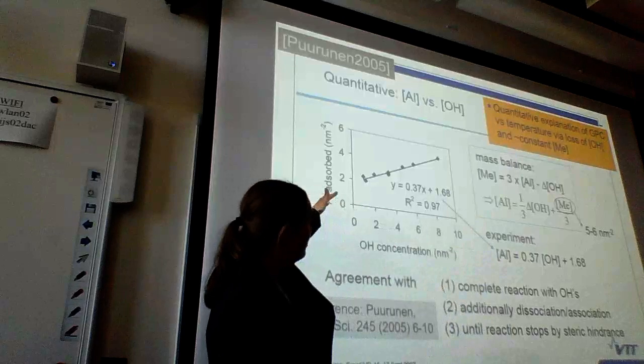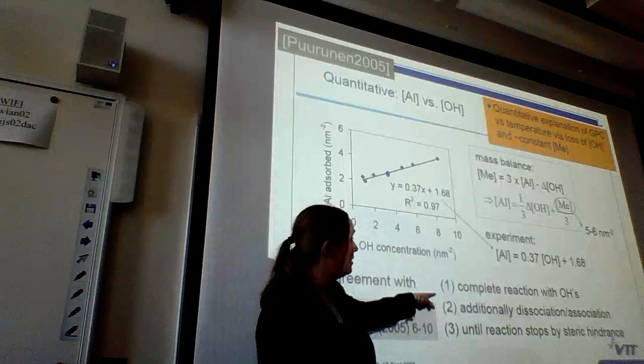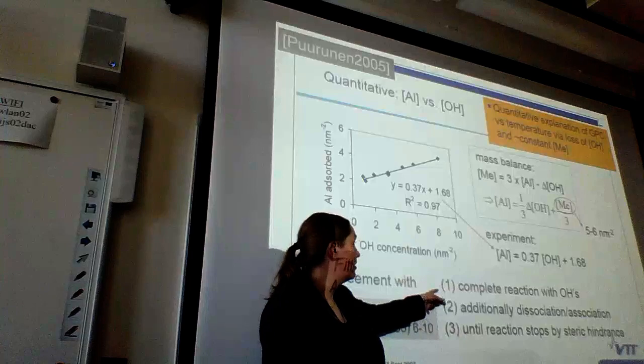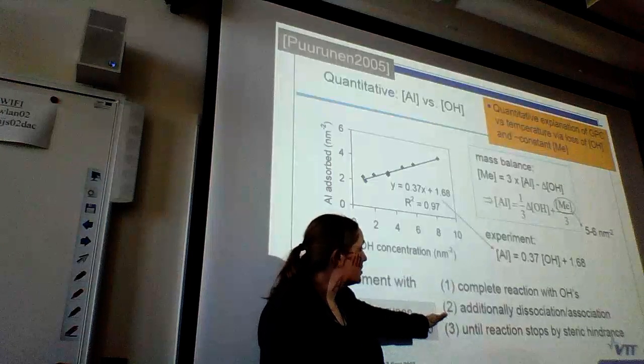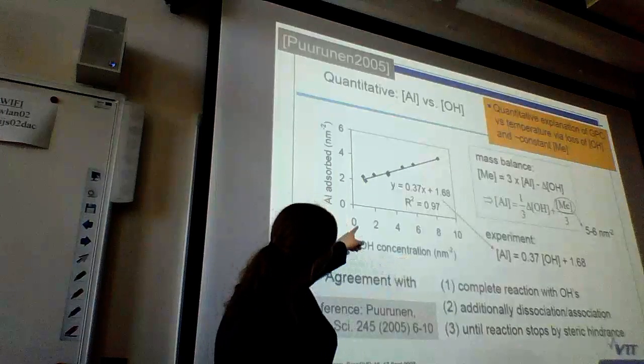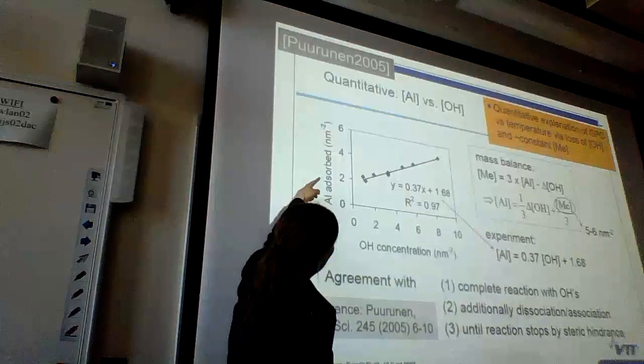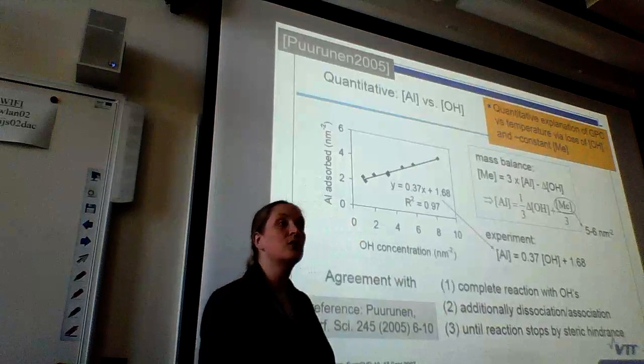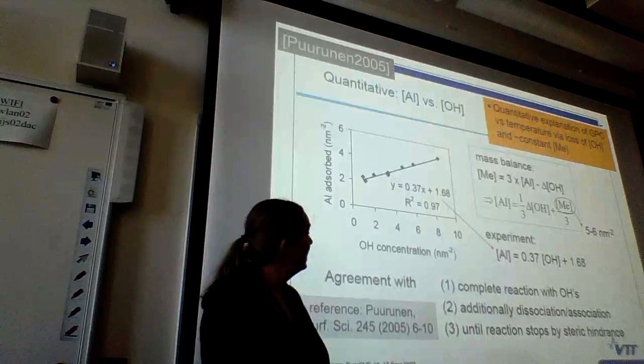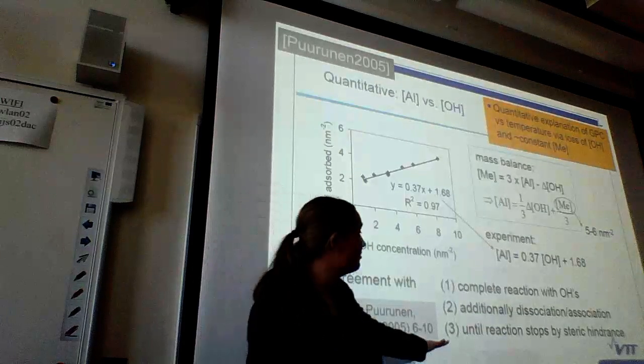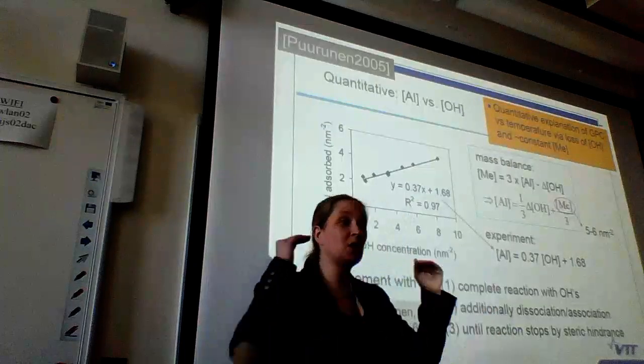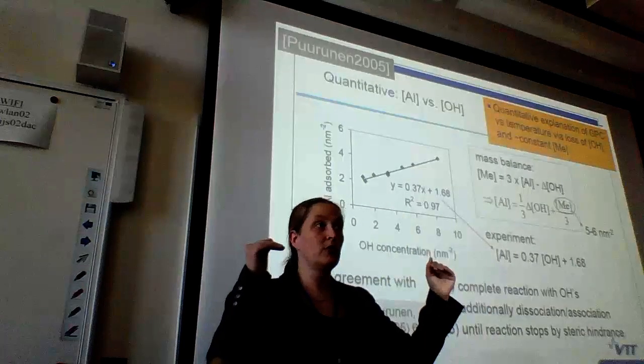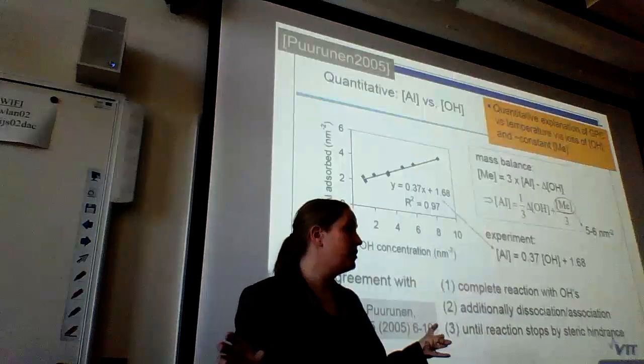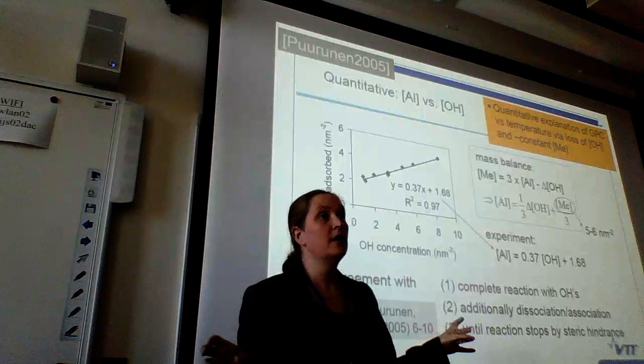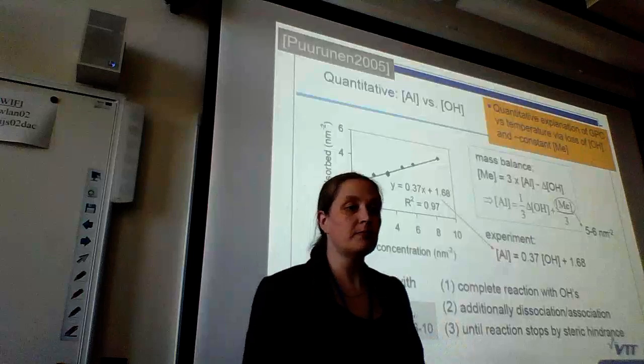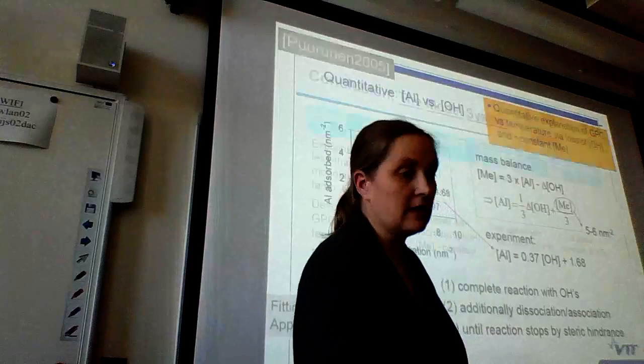So this experimental result is in line with complete reaction with OH groups, additional dissociation or association, because we actually have here a moment where we have more aluminium than we have OH groups. So it's not only OH groups. And the reaction continues until it stops by steric hindrance, because we always saw the same amount of methyl groups. When you have about 5 to 6 methyl groups per square nanometer, that's when there is no space for more. At least as I see it.